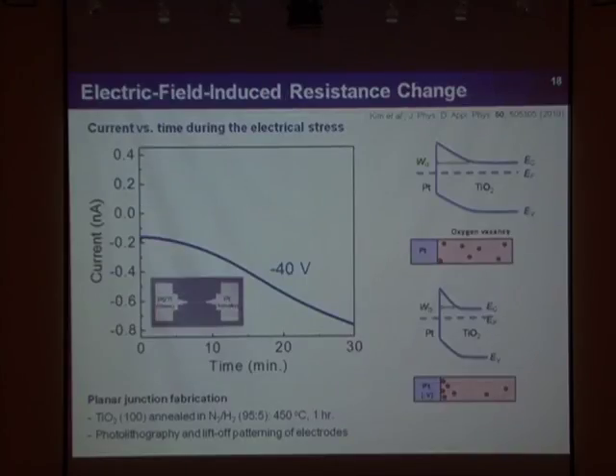So this is one of the results. This is the microscopic image of the device. When I apply minus 40 volts to the platinum electrodes for 30 minutes, you can see there is a reduction of the resistance.